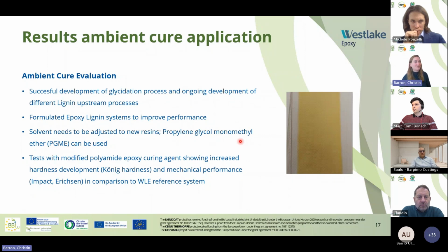As I already mentioned, we did a solvent screening and same for the ambient cure system. First of all, these solvents need to be adjusted for the new resins. And for the ambient cure system, we found that propylene glycol monomethyl ether can be used in that case. And the test with a modified polyamide curing agent could already show increased hardness, tested by Koenig hardness, and also the mechanical performance by Impact and Erichsen in comparison to the Westlake epoxy reference shows increased development.